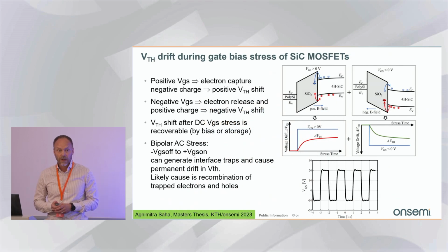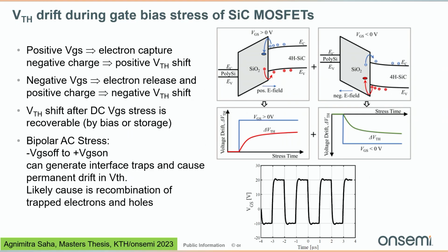To the technical side. So I will talk a little bit about threshold voltage drift during AC gate bias stress of silicon carbide MOSFET. When applying a positive gate bias to the gate, electrons are injected into interface states at the oxide. Negative charge shifting threshold voltage going positive. And when negative voltage is applied, electrons are released, holes may be captured, and threshold voltage moves negative. So this is known since a long time. It is a fully recoverable effect.